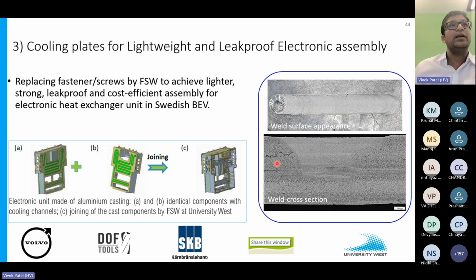not possible to weld by fusion method, especially laser welding, because laser welding aluminum with some copper creates a lot of stress corrosion cracking and hot cracking issues. So the ideal candidate was friction stir welding, and you can see the cross section of this lap joint.